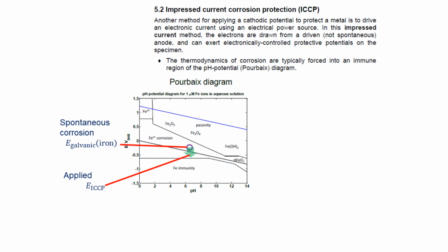Instead, we can use an electrical power source to provide the same service, because all we need to do is change the surface potential of the metal object so that the metal to be protected corrodes more slowly. And we can do that with a power source in a system called an impressed current corrosion protection system, or ICCP.